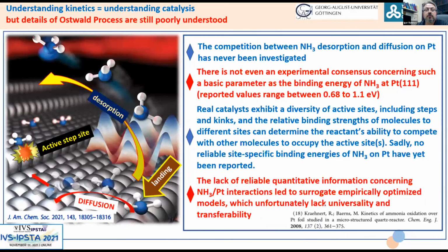So unfortunately, despite the importance of these kinetic processes, the details of the process are still poorly understood. For example, the competition between ammonia desorption and diffusion on platinum has never been investigated. In fact, even such a basic parameter, such as the binding energy of ammonia at the flat platinum 111 surface, there is no experimental consensus about it. In fact, the reported values range vastly, between 0.68 to 1.1 eV,